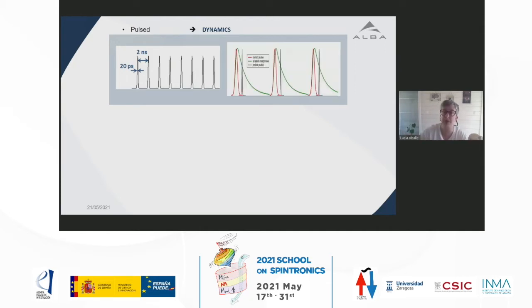This has an important consequence. In this type of measuring scheme, we excite the system somehow. It can be an electric pulse, a laser pulse, it can be whatever you want, a wave, and the system has a certain response time. It goes through certain changes, and by varying the delay between the pump and the time when our synchrotron pulse arrives, which is the probe, we can take slices at the different timings, at the different delays. What happens is that this can only be used to measure repeatable processes, so things that happen the same all the time. It is not applicable to measure emergent collective complex behavior and these kinds of things.